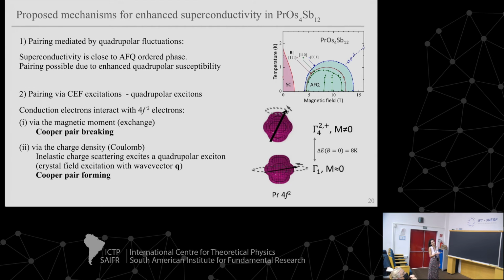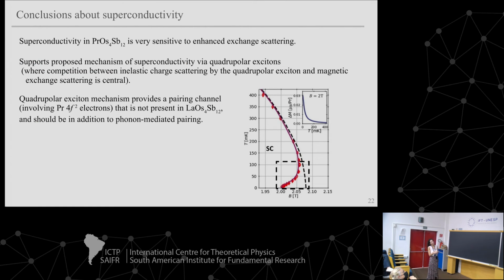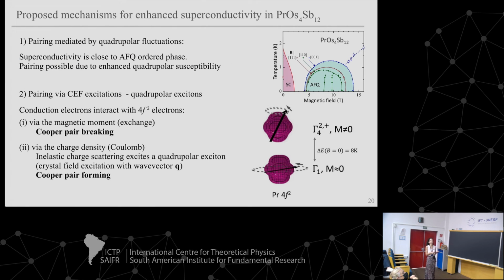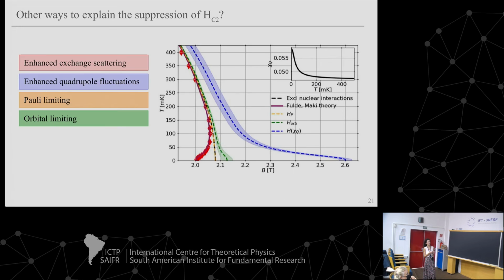And in this system, we have no moment in the ground state, so it's non-magnetic. Also, there's a large quadrupole matrix element from the crystal field. So this is an ideal scenario to realize this type of pairing. You would also expect this type of superconductivity to be extremely sensitive to enhanced exchange scattering, which is what we see, right? So we see our superconductivity is suppressed. We believe that this is because of enhanced exchange scattering. So we think that our results are a strong support for this scenario of quadrupolar exciton-mediated superconductivity.